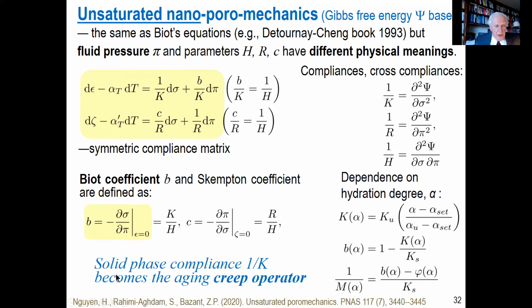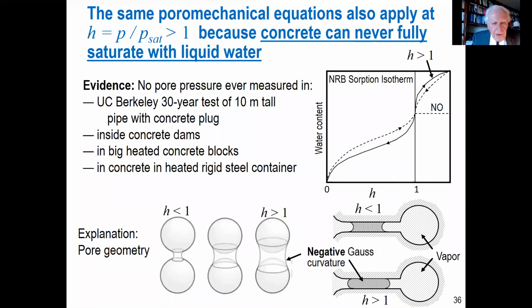Now, I must also say, because in bulk, sure, cement creeps, gives volumetric creep too, because it's porous. So this solid phase compliance, 1 over K here, must be replaced by a creep operator, and actually this R also. And that's well known how to do that. We use the same creep operator as obtained from all kinds of other calculations. And all these parameters depend on the degree of hydration, so they change with time. So it's another point which, if we know the degree of hydration, we can express.